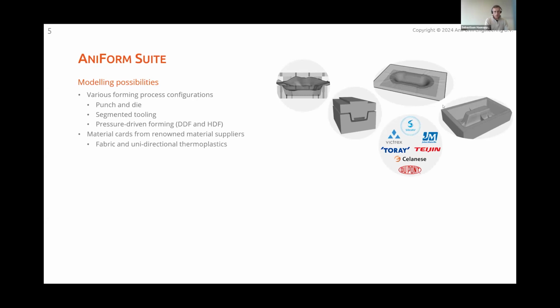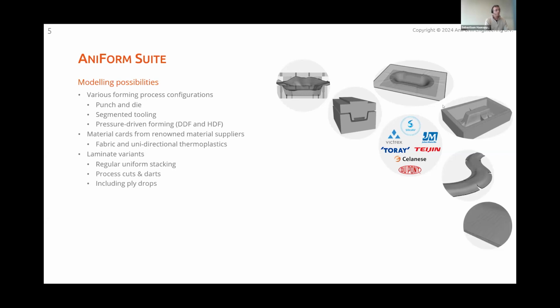You can model a material by using a material card. We have them from renowned material suppliers like Solvay, Victrex, Toray, Teijin, Johns Manville, Celanese, and DuPont, representing a fabric or a unidirectional thermoplastic composite. You can play with laminate variants. So like a regular laminate consists of a uniform stacking of plies, where you can process in the blank, for example, cuts and darts. But you can also include ply drops and model tailor blanks in this way. You can also model fiber steered or fiber placed blanks.